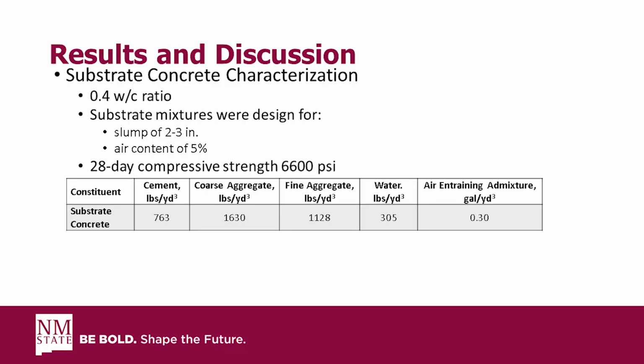Now going on to the substrate concrete characterization. So for this mix, the substrate concrete had a 0.4 water to cement ratio, and it was designed to have a slump of 2 to 3 inches and air content of 5%. And the 28-day compressive strength was 6,600 PSI, and you can see here from the mixture proportions that it was an air-entrained concrete. Okay.